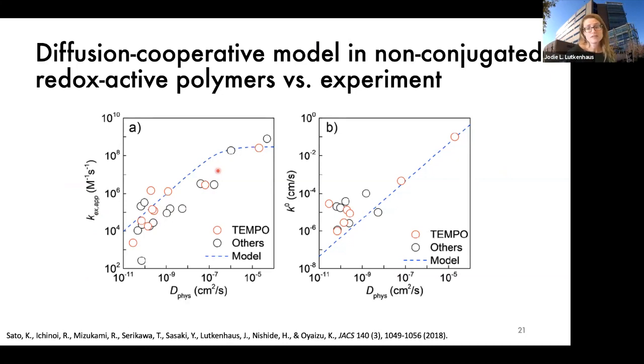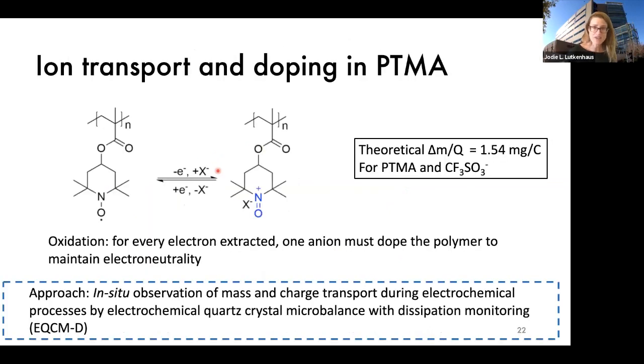So this is indicating a design parameter for all of us, which is if we want to facilitate electron transfer, which would ultimately result in higher power for your battery, we need to make the polymer as diffusive as possible. However, the problem is when you get a polymer that tends to have high segmental mobility, you're also looking at a dissolution issue. The polymer, usually the way you get a polymer to be mobile is also a way you get it to be soluble. So we'll touch upon that in a moment.